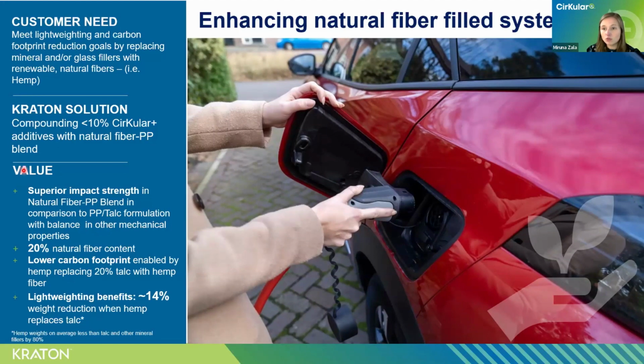So here the customer, what they wanted to achieve was to replace traditional mineral or glass fillers with a more sustainable alternative, while again not compromising mechanical performance. So here our solution was based on compounding less than 10% Circular Plus additives into a natural fiber polypropylene blend. And what we've achieved by doing that was superior impact strength compared to the conventional polypropylene and talc blends, while maintaining a balanced profile across other mechanical properties, an increase up to 20% natural fiber content, a lower carbon footprint, and most importantly, approximately 14% weight reduction.